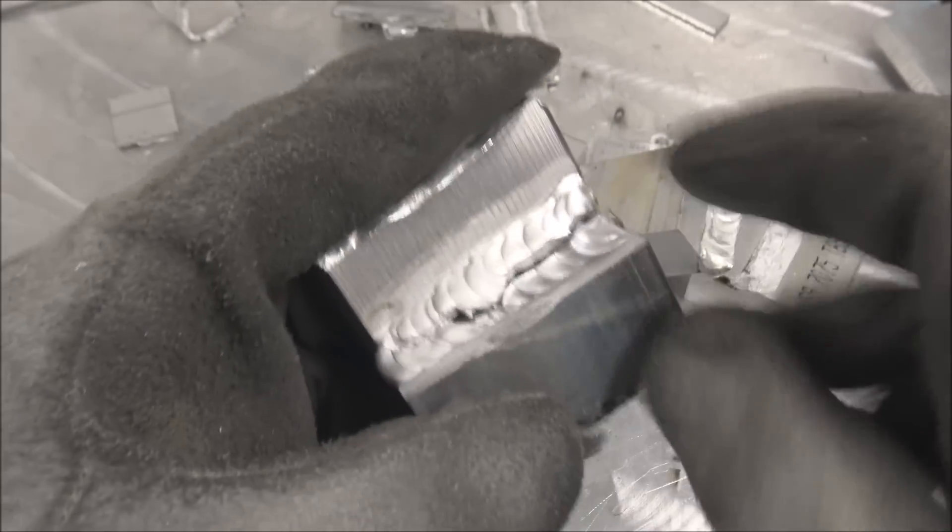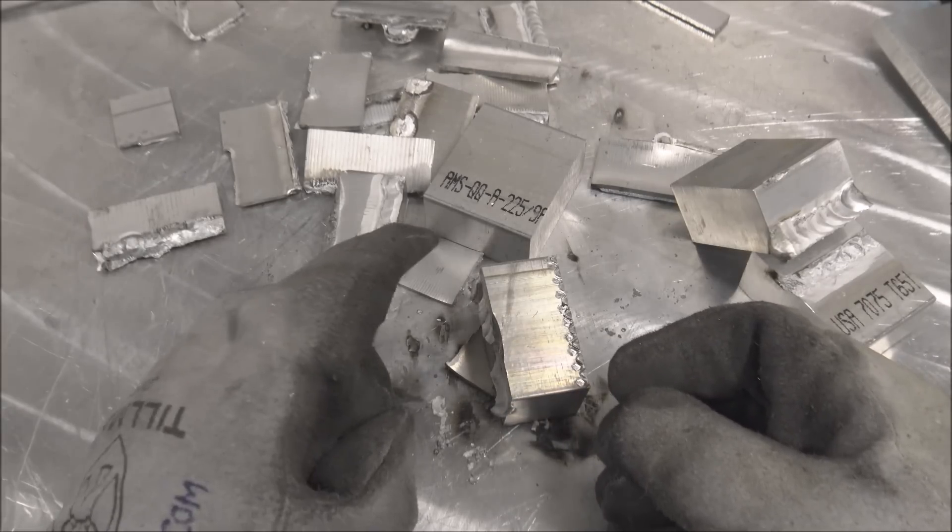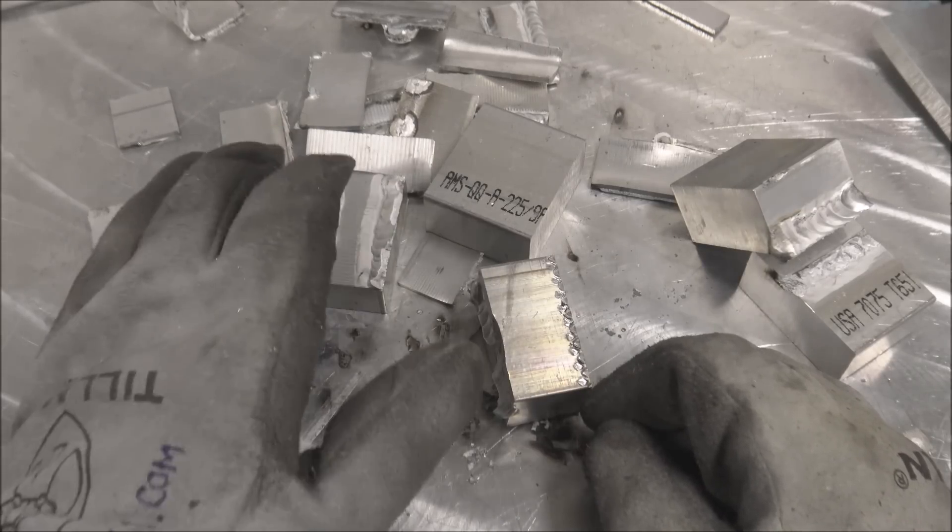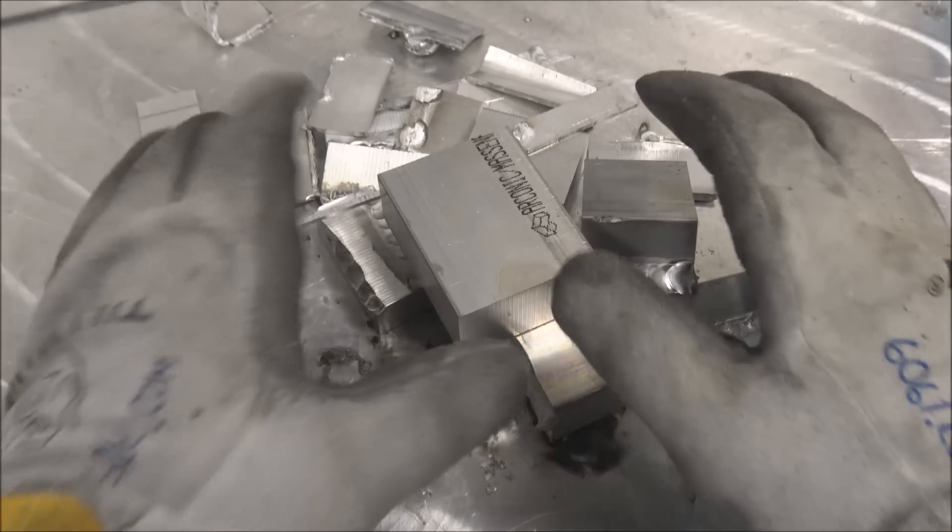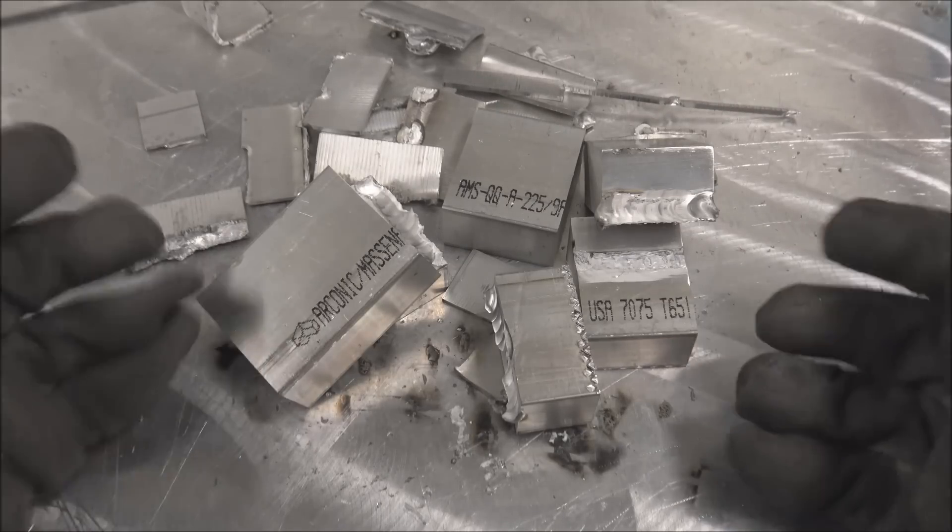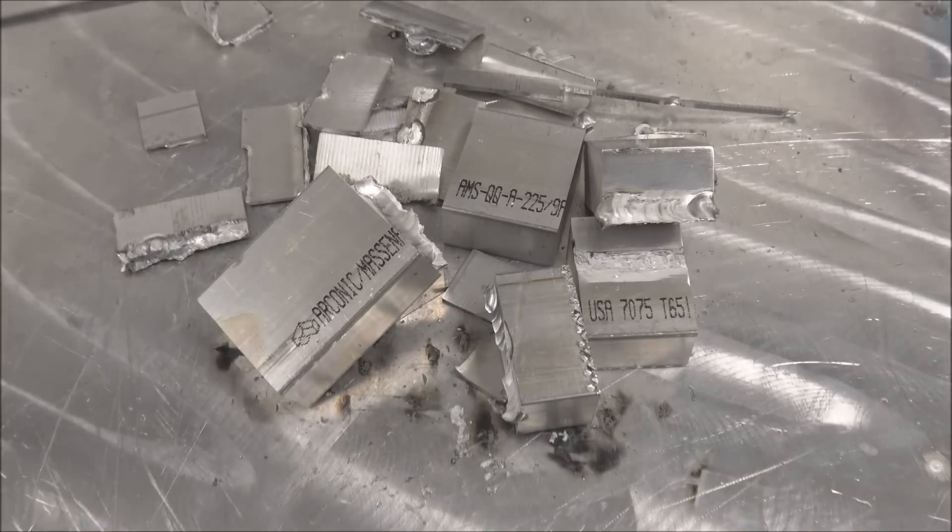So the only one that fused in somewhat decent was this bigger one where I welded it quick and tried to keep the heat down. For whatever reason, you know, like this one I tried welding exactly how I would 6061 to get it to wet in really nice and take my time, but that just seems like a no-no with 7075. So the moral of this story for me at least is if anybody wants me to weld any 7075 I'm not taking on that job. I'm just saying heck no. I don't want any liability or any rework. I'm just gonna go do what I know that I'm good at. Chunk of flat bar cost me about 30 bucks and I'm just gonna chuck it all because I don't want to mix any of this up with my 6061. So if you found this video helpful or at least entertaining please let me know by giving me a thumbs up then a comment below or subscribe and ring the bell if you want to watch more videos like these. Thanks for watching.